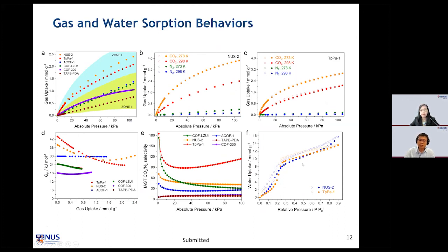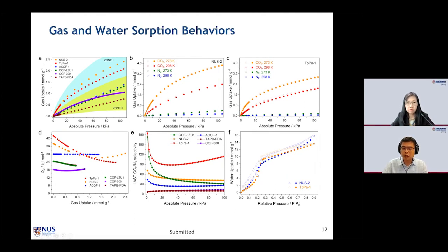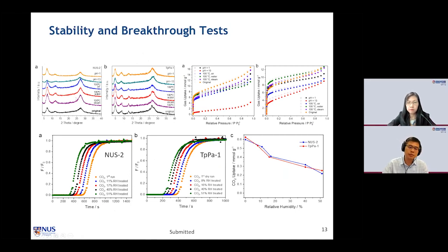We found that compared to MOFs, one take-home message I want to share is that COFs are hydrophobic. You can see this from the S-shaped water uptake. And you may wonder why this S-shape is interesting. Oh, by the way, we tested the stability. They are very stable in water.